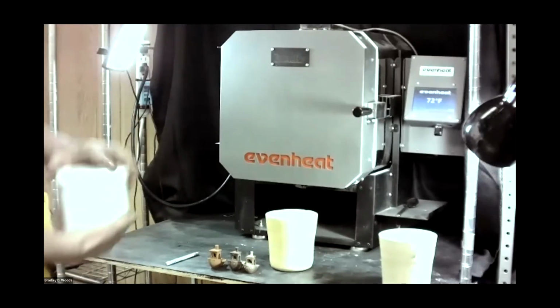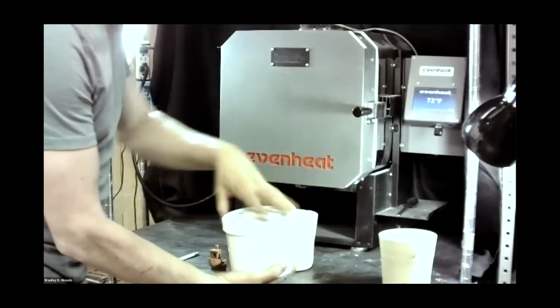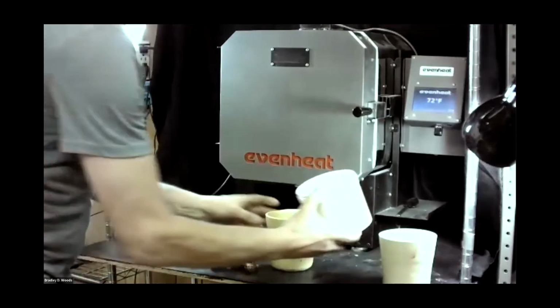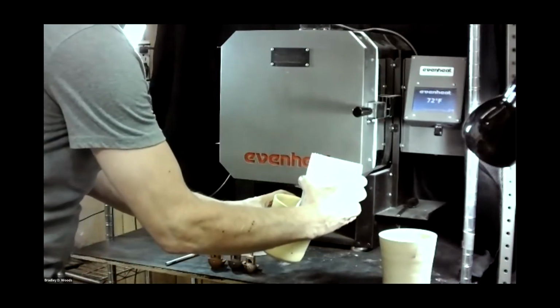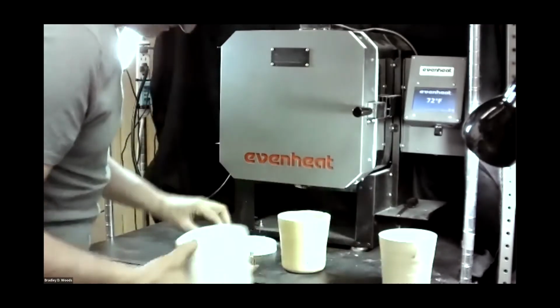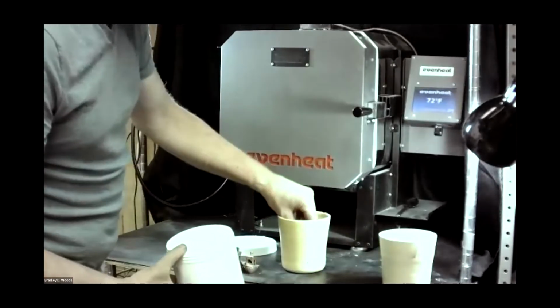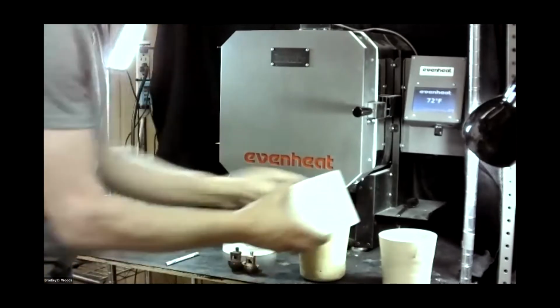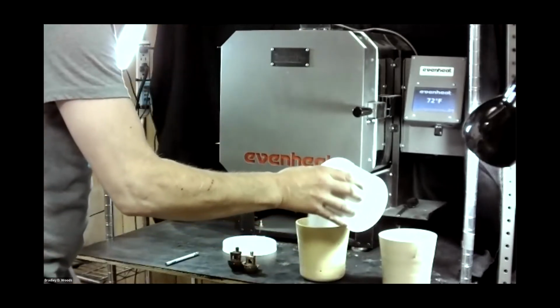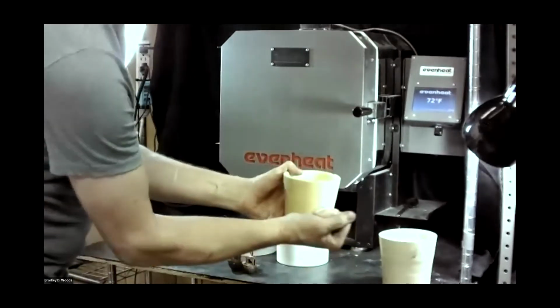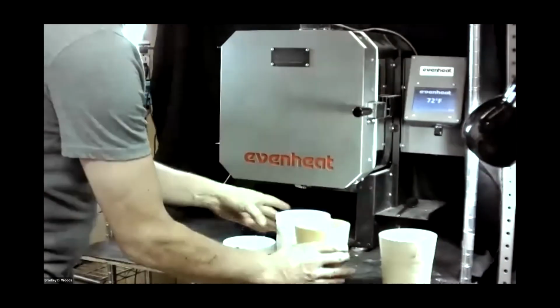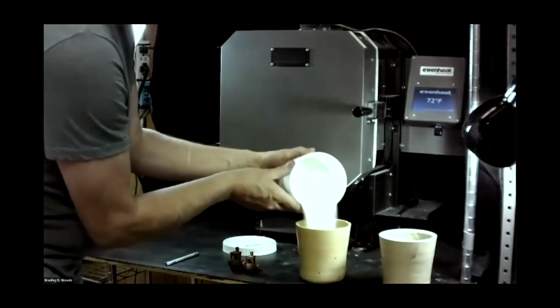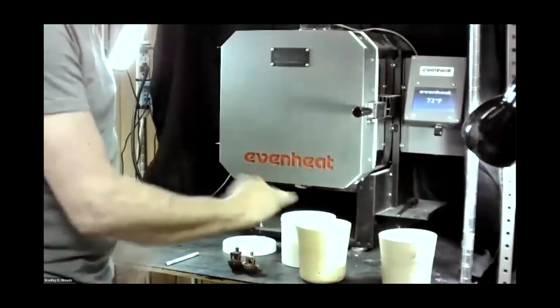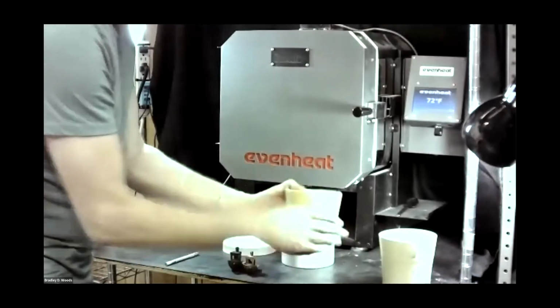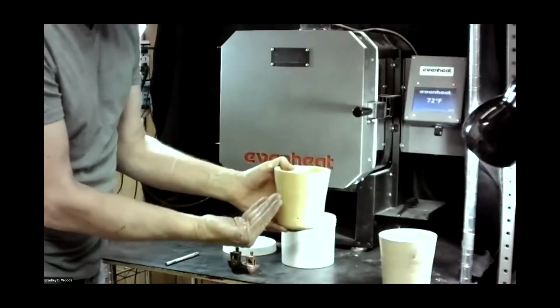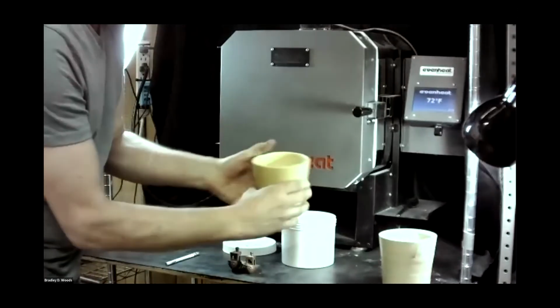Okay, so for step one, this is the Al2O3. So all we do, take a crucible, fill it about halfway up. Set the green part on top of what you've already put in there. Add a little bit more. I like to shake it around so it settles in nice. Make sure there's no air gaps left. If your print has bridging in it, you want to give it an opportunity for the Al2O3 to get under it. And that's where this happens.